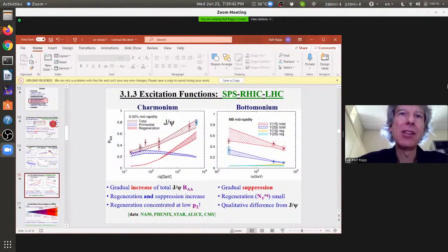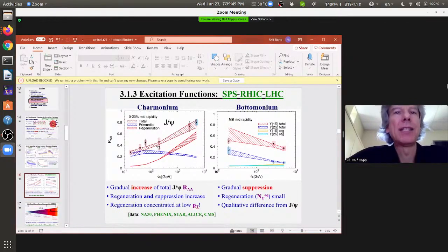What determines, so then you ask, why is it so strongly suppressed already at SPS? That is what we now understand due to these very nice NA50 and NA60 measurements of J/psi suppression in pA. There's a large suppression in pA at relatively low energies, around 20 GeV or so. There's a very large dissociation of the J/psi already in pA. That goes away as you go to high temperature, high collision energy.